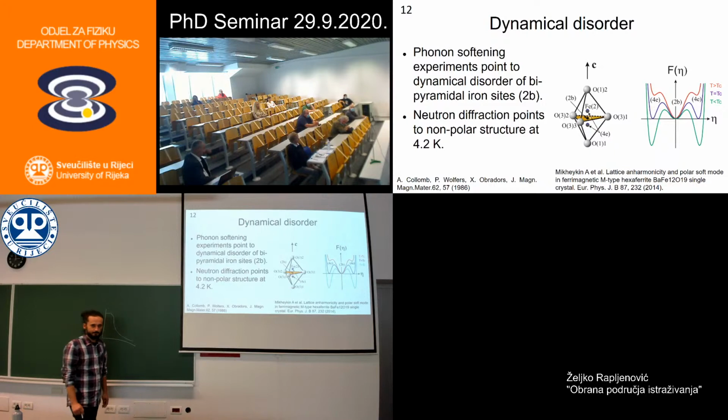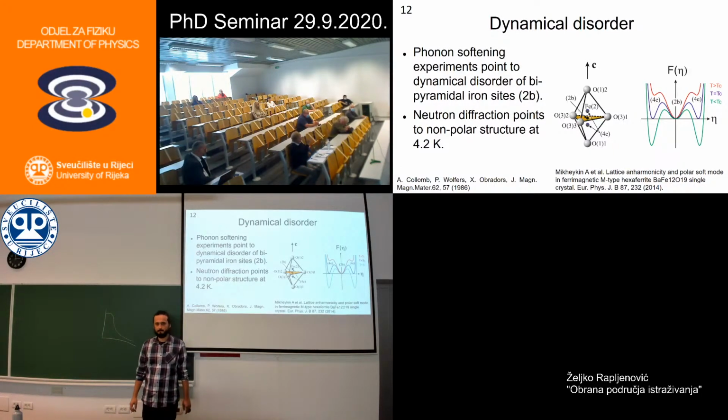So the dielectric constant follows so-called Barrett behavior, which actually means that there is polarization down to extremely low temperatures. But there is deviation from Curie-Weiss. There is no ferroelectric ground order due to quantum fluctuations.